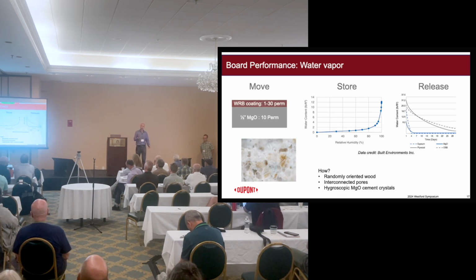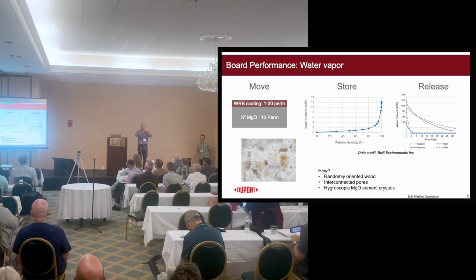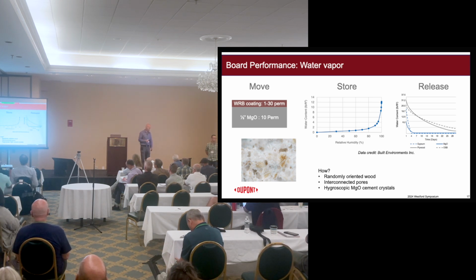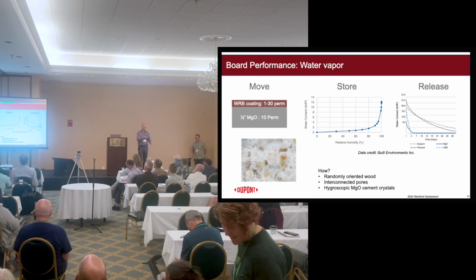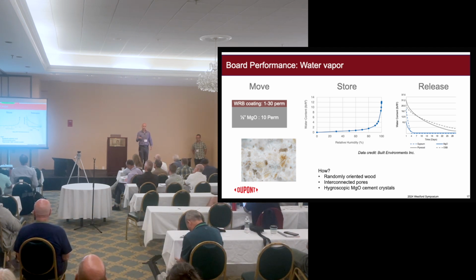A couple other things. The early interest in this material was really driven by its response to moisture. That is, its ability to move moisture around inside of the board. If you get a point source of moisture, it's able to move that water around, and then able to release it back into the environment. This is some data from the testing firm Built Environments, where they were able to show that even a fully wet board on the right graph is able to release water even faster than, for example, some of the common wood-based products, plywood and OSB. But on the flip side, it's able to act as a reservoir for some amount of water, absorb it from the atmosphere, and then again later release it.